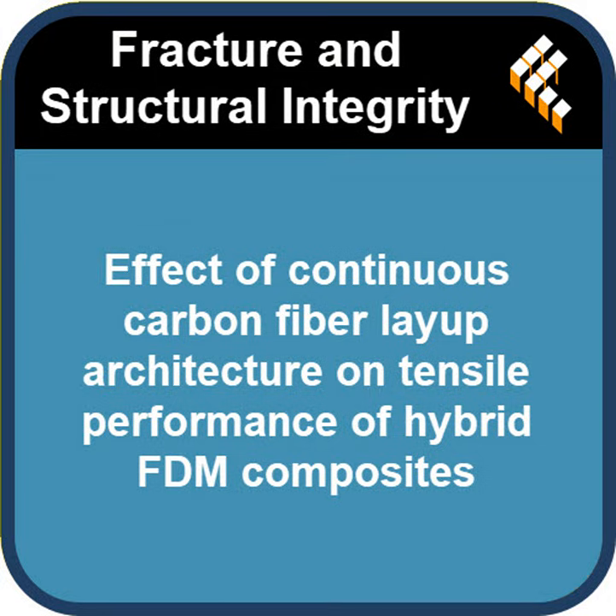You do. And the type of plastic acting as the glue around that spine plays a huge role in absorbing the remaining impact. Like ABS proved to be highly brittle when the angles changed. But the PETG matrix still acts as the ultimate shock absorber, right? Exactly. When paired with that 30, 0, negative 30 architecture, PETG achieved the highest ultimate strain overall. It actually stretched by nearly 3% before finally giving out. That is a massive amount of energy absorption for a structural component.